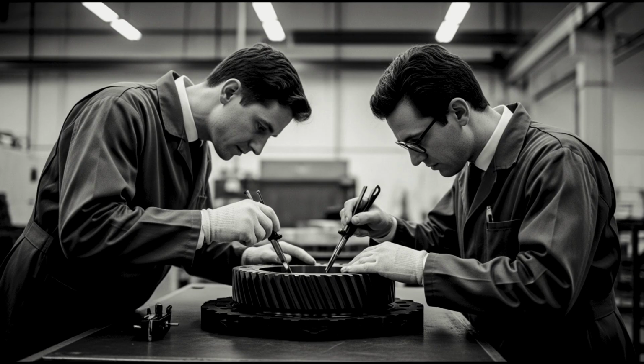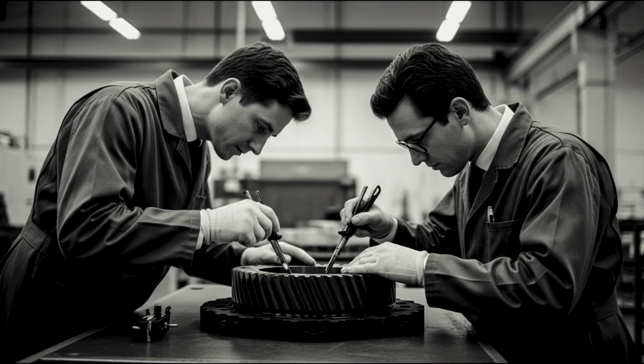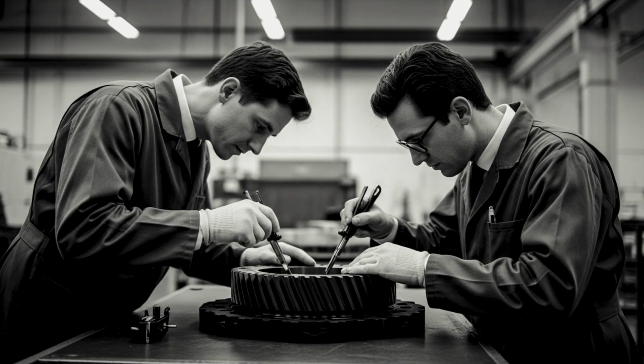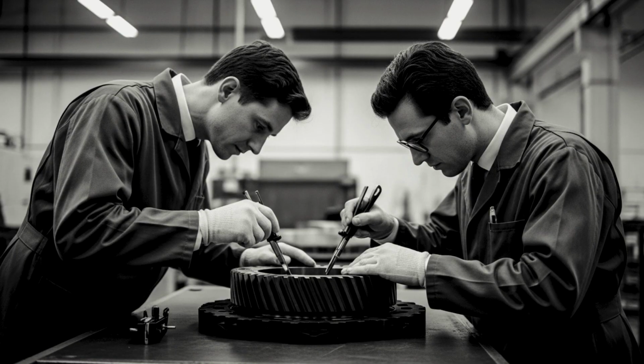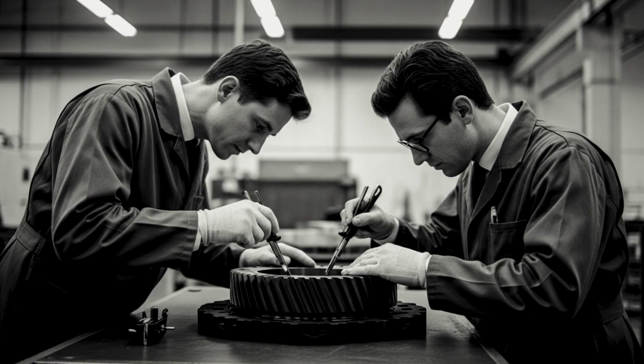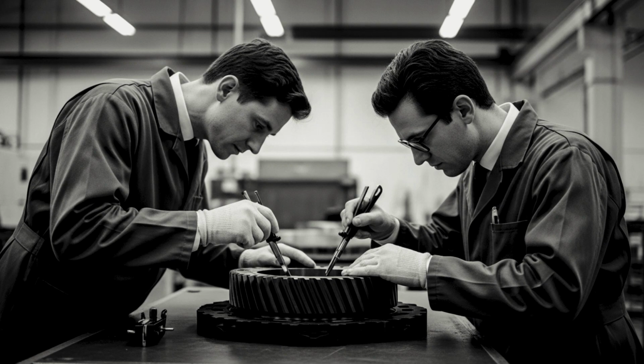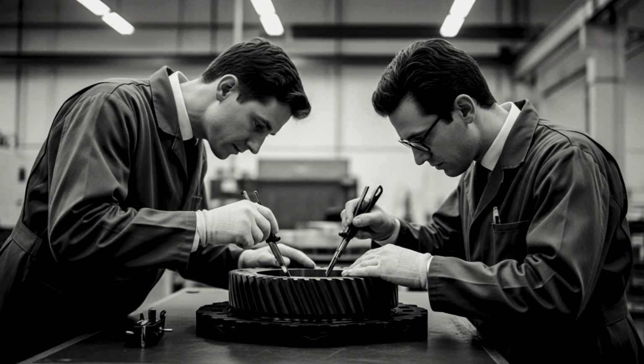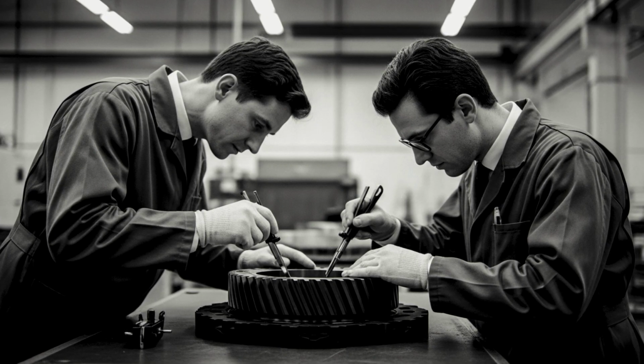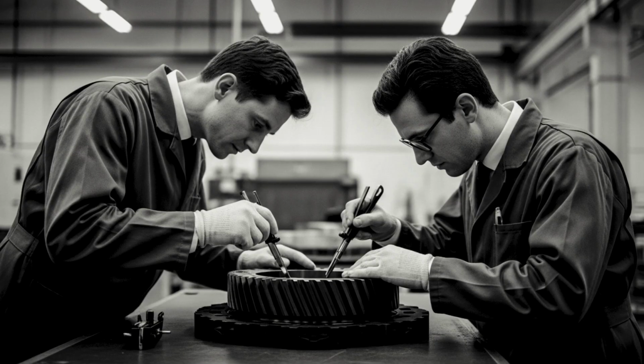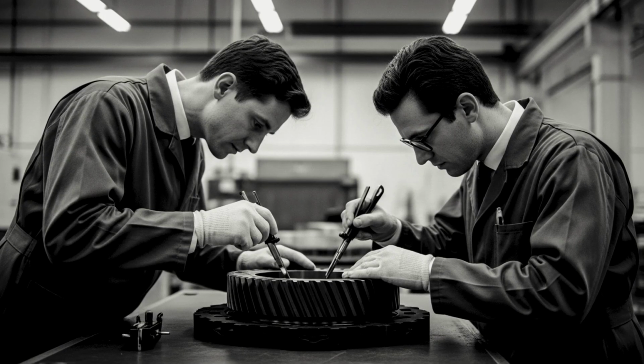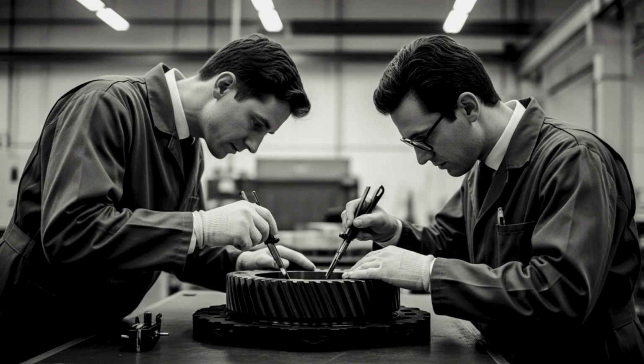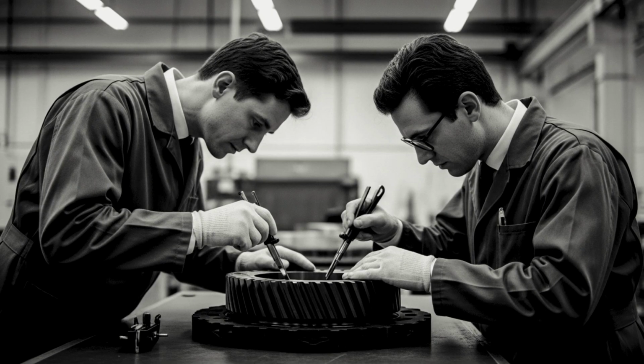Stevenson inspected 6 other broken Tiger gears. Each one showed the same pattern: too hard on the surface, hardened too deeply, and no proper tempering. Every single one had snapped in the same way. This showed that the problem was not just one gear or one factory. It was happening in all Tiger transmissions. All the gears were too hard and too brittle. They could not survive normal use, let alone the heavy stress of combat.